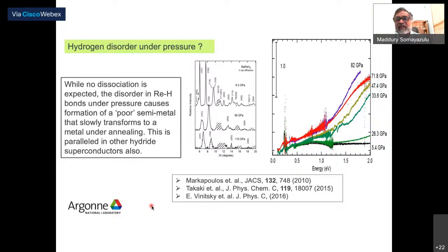But we can also do Raman spectroscopy, and that is something which I will not talk about here. But what was surprising to us, it's a really interesting result, is that while there is no dissociation, the disorder in the rhenium-hydrogen bonds under pressure seems to cause it to form a poor semi-metal. How do we know? If we look at reflectivity, and you can do the analysis of the reflectivity in these materials, what is traditionally known as the Tauc plots, you see two kinds of linear regimes. It's almost as if the material is a poor semi-metal.